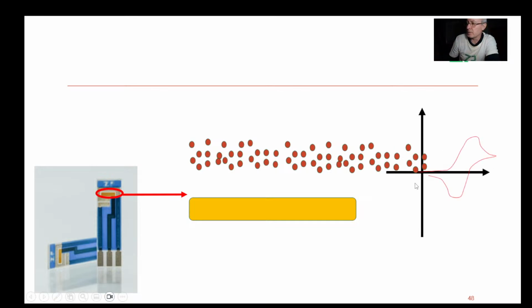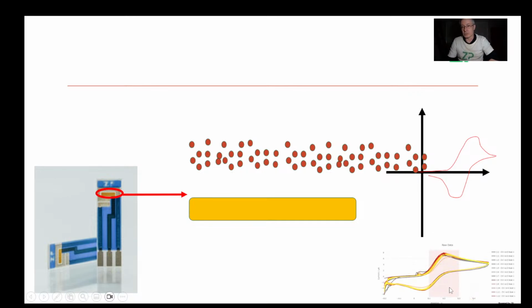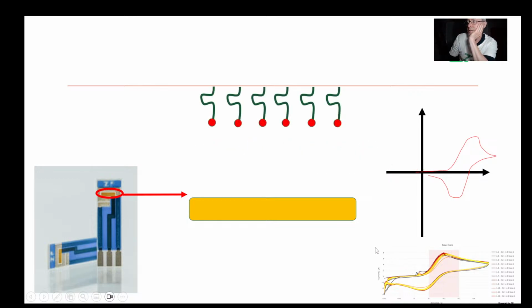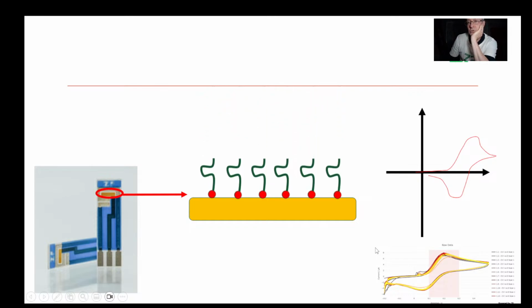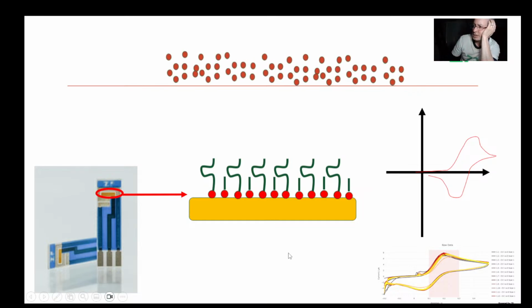I'm sure you're doing the same, but after you've activated the surface and rinsed that gold electrode, you should check it. We would actually check it with ferrocyanide and just make sure that we got a good CV off it. And you can check whether you've got a good CV by looking at the data that I showed previously in these slides. If you've got a good CV, then you've reduced your disulfide to a thiol. You can put that thiol on there. I noticed you didn't mention anything about a spacer, so MCH is a good spacer. You should have that in there as well to keep the molecules apart, and then you should be quite good to go.